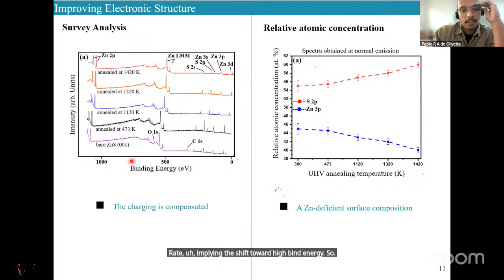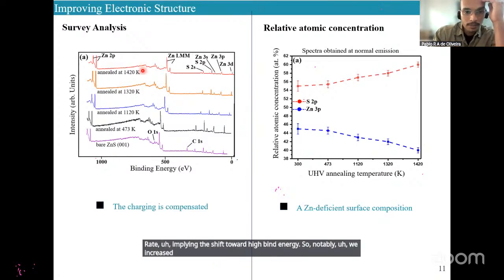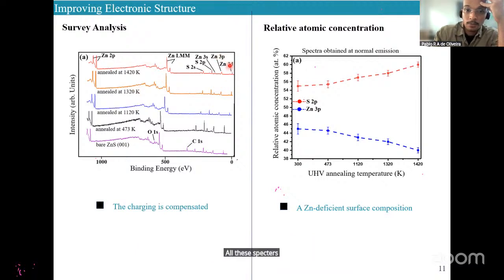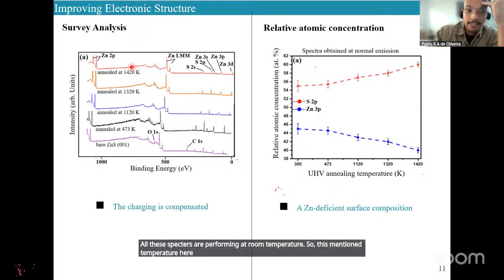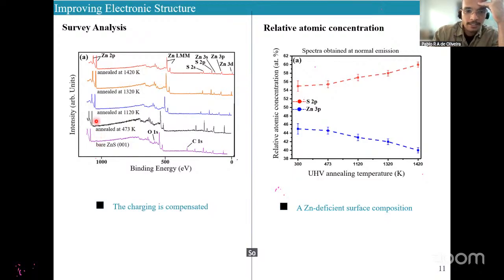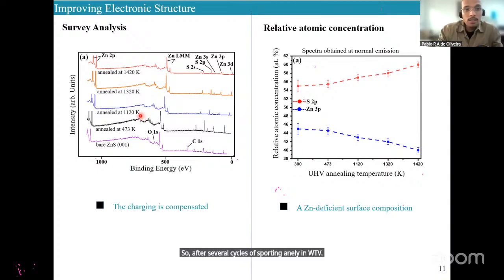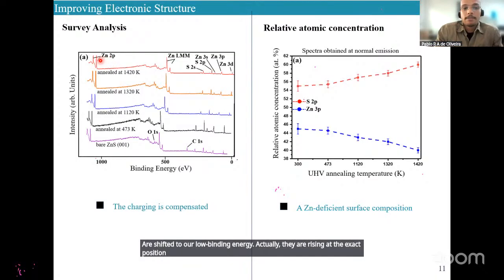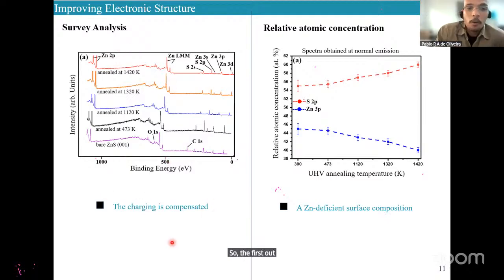So notably, we increased the annealing temperature. It's worth noting that all the spectra are performed at room temperature. So the temperature mentioned here is the annealing temperature before the measurements. So after several cycles of sputtering and annealing in UHV, we noted that peaks are shifted toward low binding energy. Actually, they are rising at the exact position as expected for the ZnS system. So the first outcome is that the charge is compensated in the system.